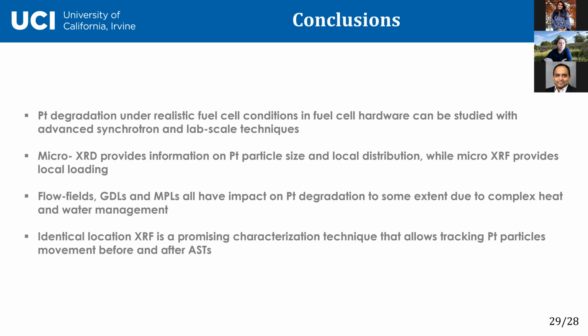So lastly, in conclusion, we looked into platinum degradation, looking from perspective of what the flow field does to it. We found that if you have a flow field that has really wide lands and channels, then it affects platinum degradation, it's not homogeneous. Looking into GDLs, gas diffusion layers don't seem to affect platinum degradation, but we found that microporous layers with cracks seem to result in more platinum being lost, carried out from the system, and we think it's just platinum ions being carried by water that leaves the system.